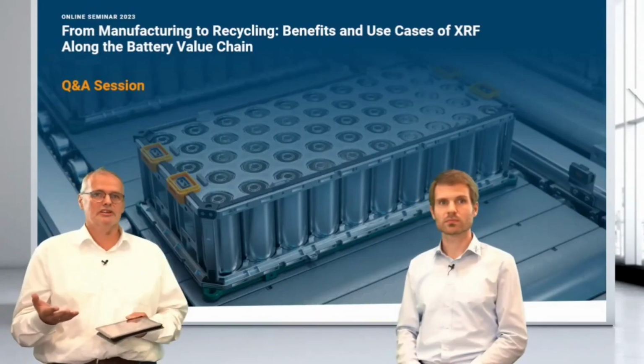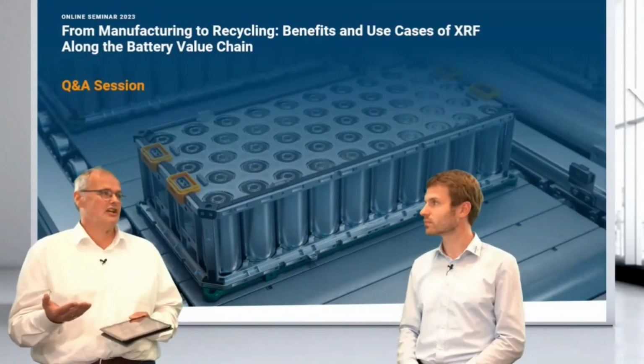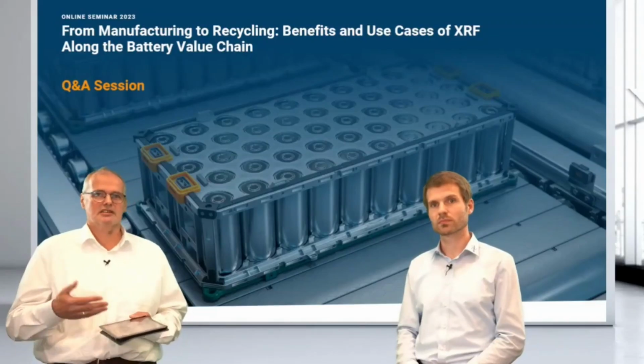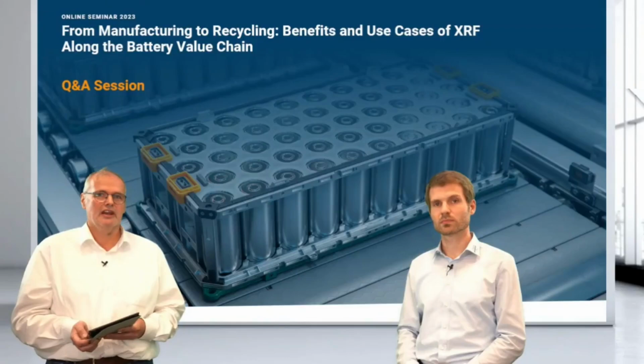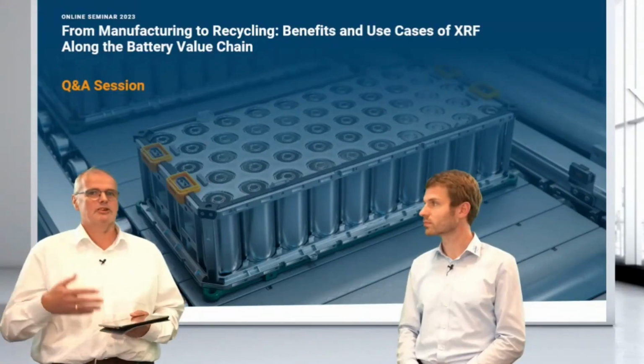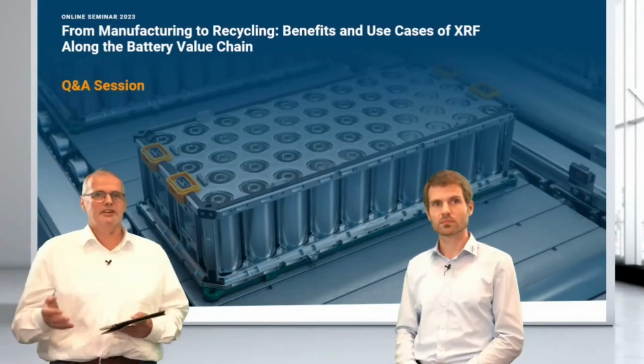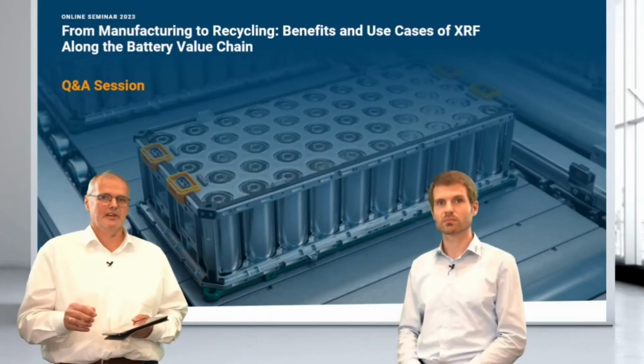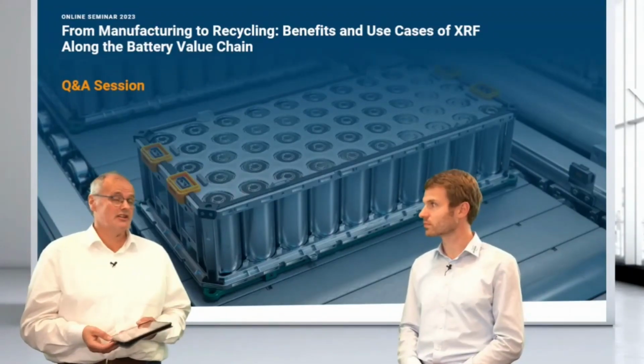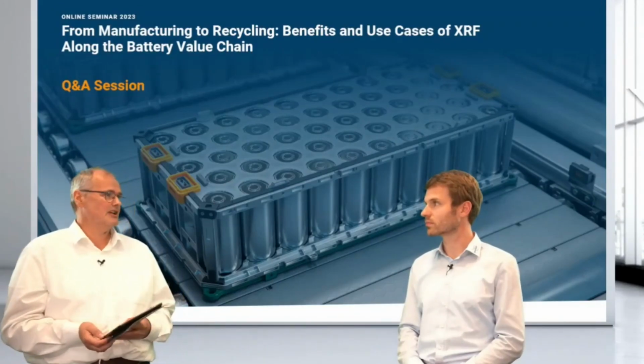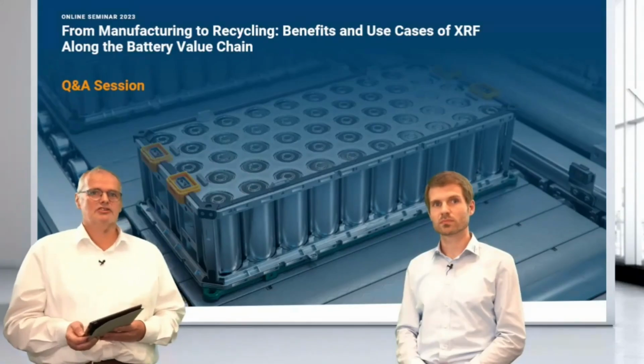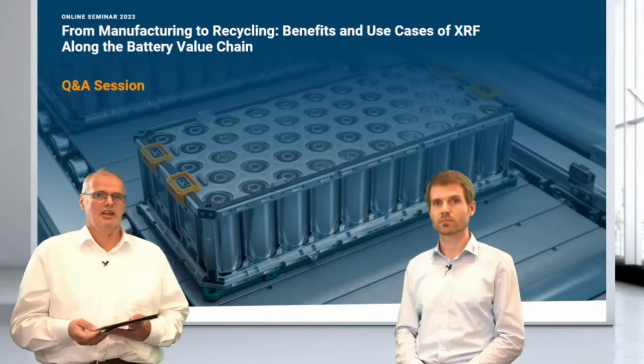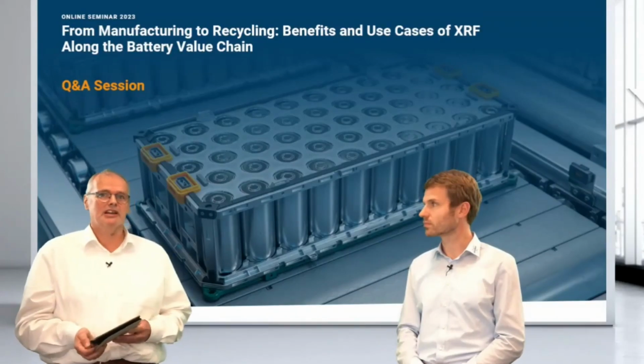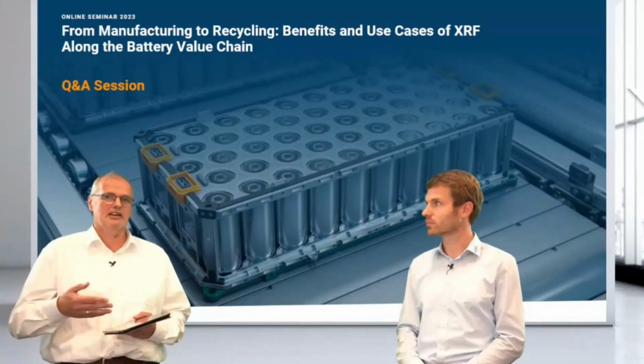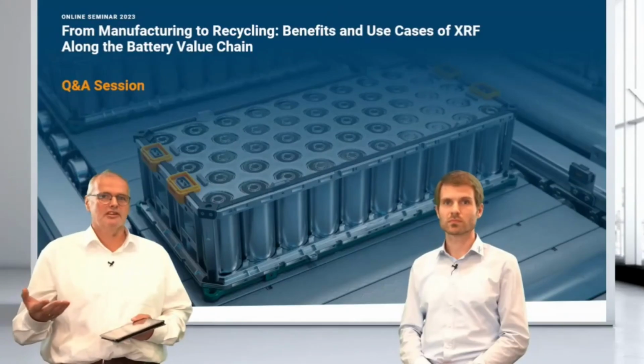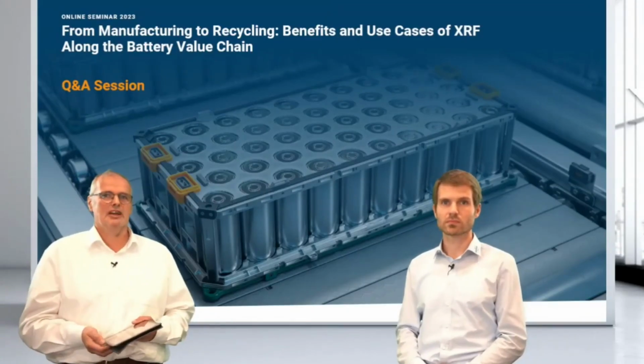So this is the one thing. The second thing, which is more critical, is that there is not much fluorescence radiation coming. Most of the energy is expelled as an Auger electron, and this cannot be detected by our instruments. There must be ultra-high vacuum devices. So there will not be a way to determine lithium directly. What is good, as I said, is that we can access the matrix indirectly, and this is already a very big help to get an estimation about the range, and often this is good enough. We have instruments installed in lithium mining applications analyzing the rest of the elements, and then, knowing the stoichiometry, we can estimate the lithium content pretty well.